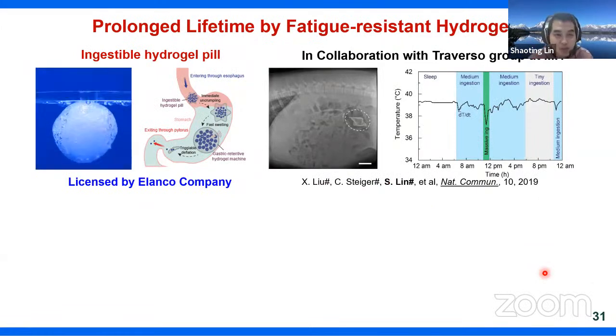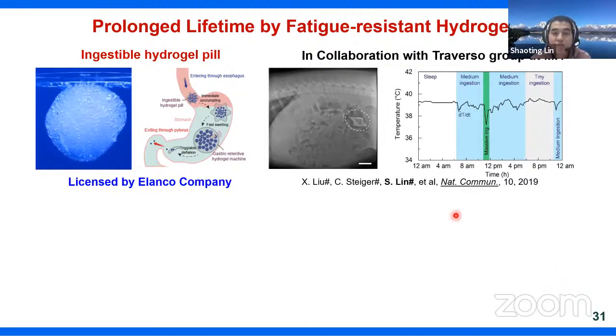Now going back to applications, we are fortunate to further demonstrate two close-to-real applications by leveraging these fatigue-resistant hydrogels and hydrogel adhesions. We first used the fatigue-resistant hydrogels to extend the lifetime of a hydrogel-based ingestible device. We collaborated with the Traverso group, and this is a large animal test. We successfully demonstrated 30-day retention, and we further incorporated temperature sensors. We demonstrated 30-day temperature sensor recording. This is a 1-day temperature recording, which can clearly show dietary activity in this pig model.